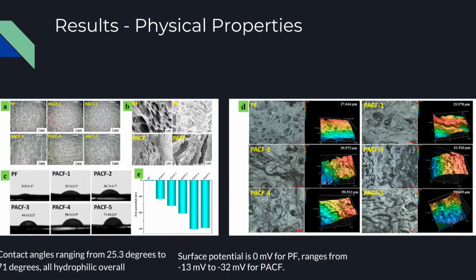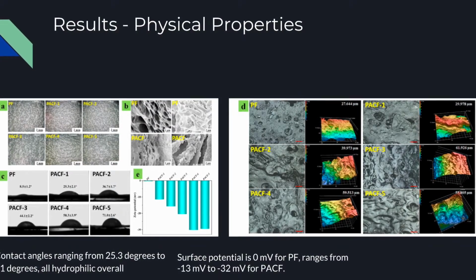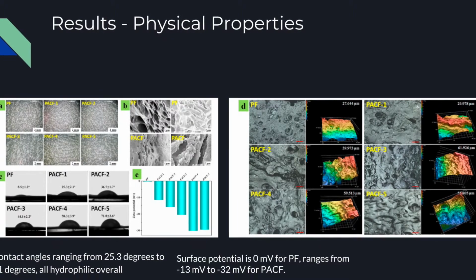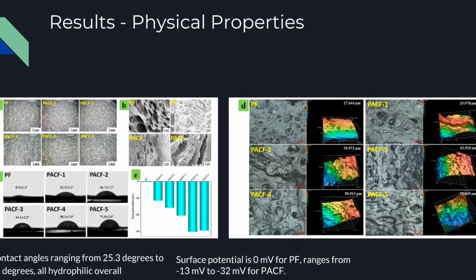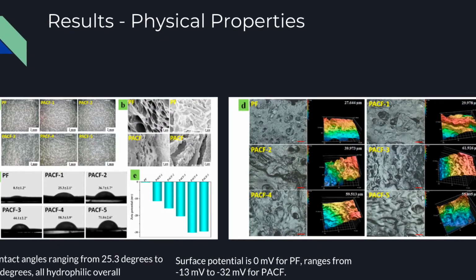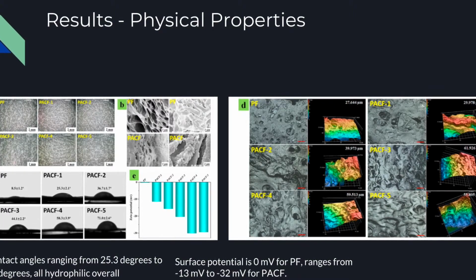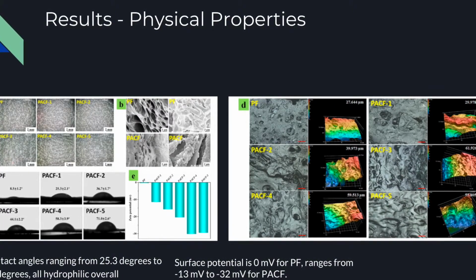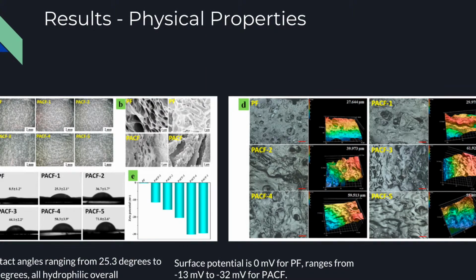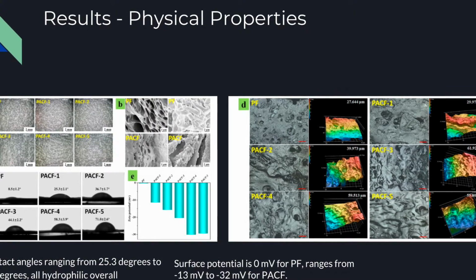But all were still lower than 90 degrees, so were hydrophilic overall. Surface roughness increased with alginate concentration, and therefore surface area increased, contributing to platelet and plasma protein adhesion, and surface potential decreased because of increasing carboxyl groups from alginate, going from -13 to -32 millivolts.